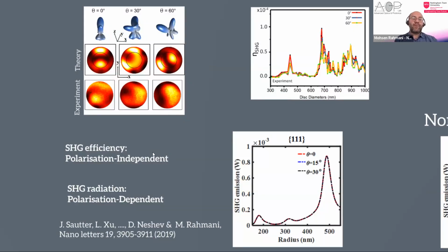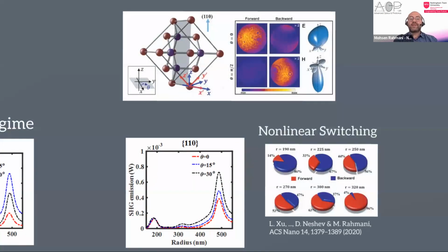So a very interesting thing about this 111 gallium arsenide nanoparticle is that the second harmonic efficiency is polarization independent, but the second harmonic radiation is polarization dependent. It means that when you change the polarization, the efficiency doesn't change, but only the emission changes, which is very exciting. And 110 is even more exciting, because only by changing the polarization of the input, you can control the forward and backward, and you can switch the second harmonic generation from forward to backward scattering, which is very exciting.